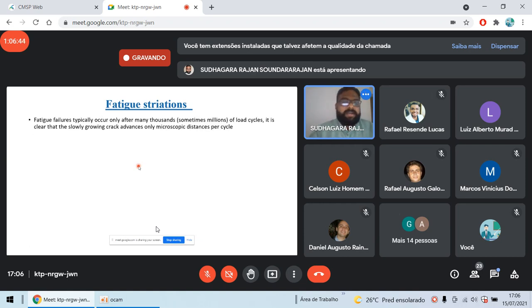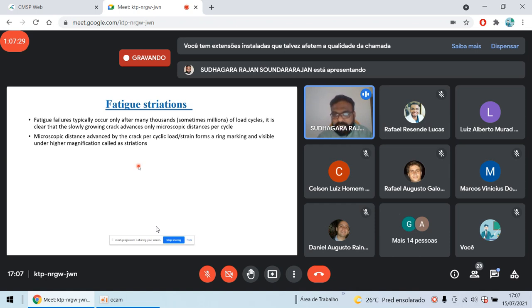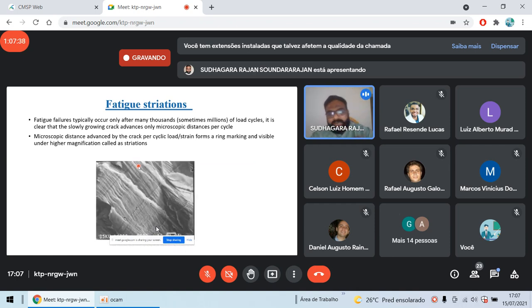Here come the striations, just the opposite of that. Fatigue failure typically occurs over many thousands or sometimes millions of load cycles. For each and every load cycle, the crack will advance practically. Am I right? If the crack is advancing, it will leave a footprint, an impression, for each and every cycle. That impression is nothing but the striations. So the crack advances only a microscopic distance per cycle. That is very important. So this feature you cannot see with the naked eye. The microscopic distance advanced by a crack per cyclic load or strain forms a ring marking. This is also a kind of ring marking, but it's very closely packed and it's a microstructural feature, visible under high magnification, called striation. This is how it looks.